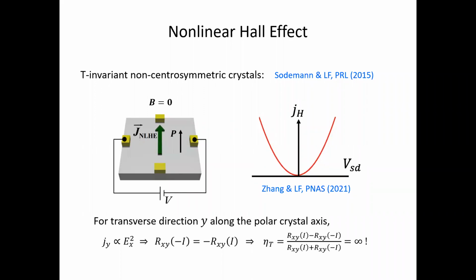And this kind of IV curve is nothing like anything you've seen before. It's different from Ohm's law. It's also different from the case of a PN junction diode. Okay, but we predicted that this quadratic IV curve should occur in non-centrosymmetric materials at zero magnetic field. Now, this is really the most extreme form of non-reciprocal effect, right? As you reverse the direction of the voltage, the current actually stays in the same direction. The current stays the same. And indeed, if you take the formal definition of the diode coefficient, you find that it exceeds 100% and it diverges.